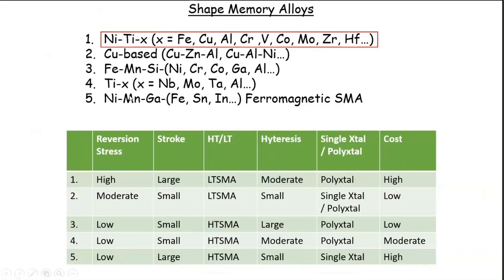And of course, titanium shape memory alloys, one can imagine, are biocompatible, so they'll have some application in the human body. But more than that, they are biomechanically compatible. If you start with something like porous titanium-based alloys, the biomechanical compatibility comes because the modulus is close to that of bone. Porous titanium-based alloys will have a modulus very close to about 10 to 12 GPa, which is quite good and close to bone.